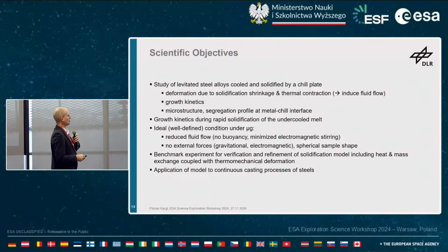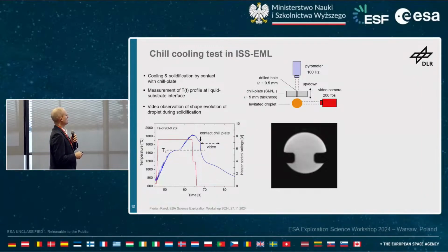It's growth kinetics during rapid solidification of the undercooled melt that one can look into, and you have, again, well-defined conditions under microgravity, so reduced fluid flow, no buoyancy, minimized electromagnetic stirring, no external forces, spherical sample shape, so ideal conditions to start modeling this process and understand it better. And the space station experiments are really a benchmark for verification and refinement of the solidification model that includes heat and mass exchange coupled with a thermomechanical deformation. And then one can apply this to the continuous casting process of steel. How does the experiment look like?